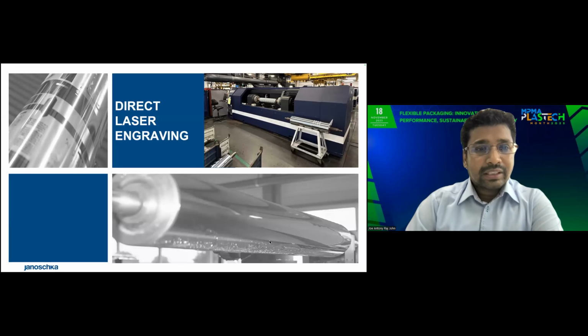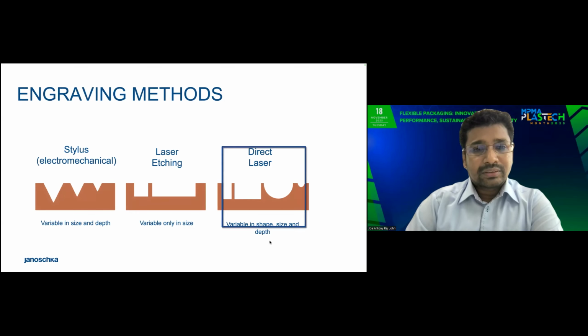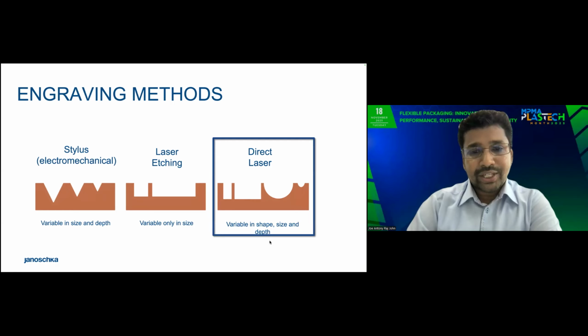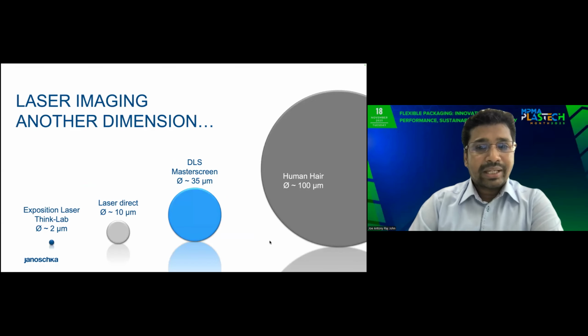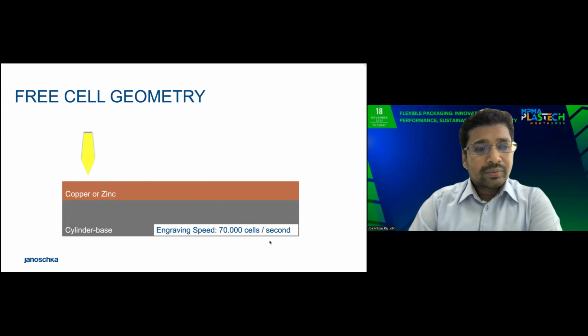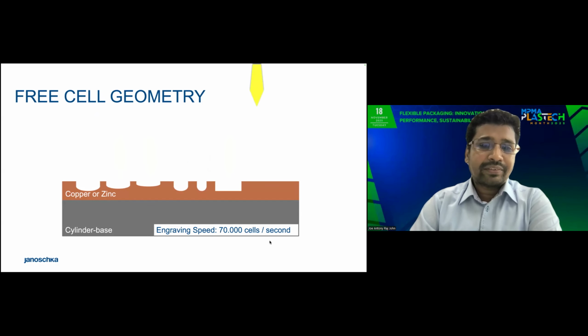The next technology we're talking about is direct laser engraving. This technology gives us variable shape, size, and depth. As you can see, a human hair is 100 microns, whereas our DLS master screen can engrave 35 microns with a laser spot of 10 microns. With the exposition of ThinkLab, it can go down to 2 microns. The laser is exposed on the zinc or copper surface, which engraves 70,000 cells per second, with various shapes, depths, and sizes.